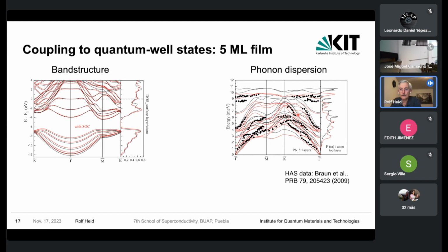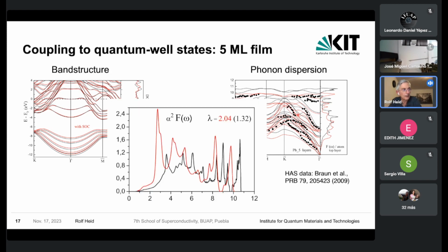And finally, having all these ingredients and including now the calculation of the electron-phonon coupling, we can calculate the Eliashberg function, which then describes the pairing interaction in the context of superconductivity. And here you see, now just look at the red curve where the spin-orbit coupling is included. Indeed, a very strong coupling, particularly a coupling very strongly to modes with relatively low energy. This is the scale of meV here, the phonon frequencies in meV.